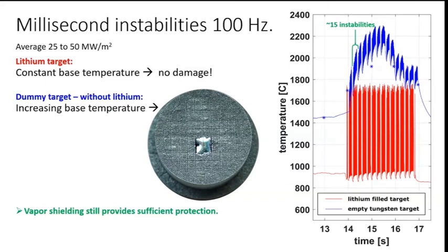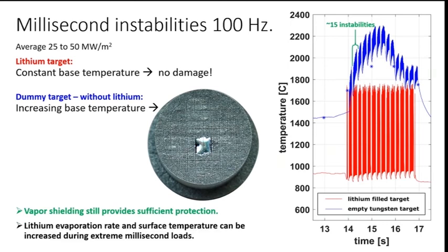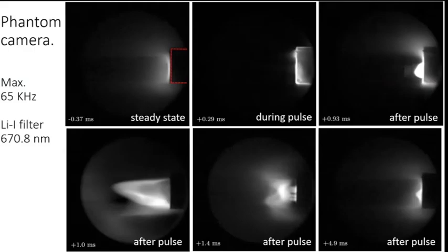And keep in mind, in a fusion reactor, the steady state heat load that we aim for is about 10 megawatt per square meter. So this is well above that. Yet the target survives. But again, we should note evaporation may be significantly increased in these cases, right? Because to deal with these extremely high loads, we will get increased temperature, despite the temperature locking effect, to evaporate enough lithium. And in fact, now I'll show you some of these camera images.